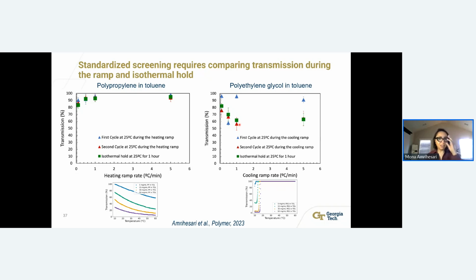So when we are looking at a high throughput data collection, we want to make sure that this data is reproducible. That's why we kept it not only for 1 cycle, but for 2 cycles to match and look for reproducibility of the data. For that reason specifically, we collected all the data for high throughput experimentation during the second cycle for all these cases and during the isothermal hold. So these results show that the first cycle is not matching. So we have to be mindful of what is the kinetics, what type of material we are working with. But the second cycle, since it's matching, is reliable data for further collection and faster data collection.